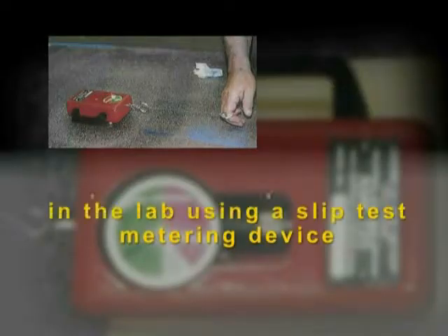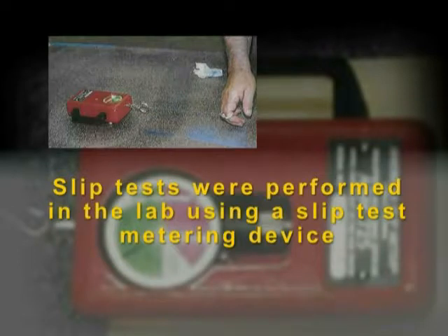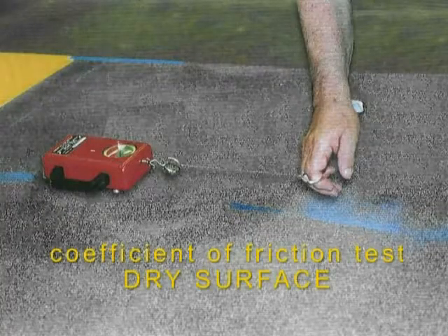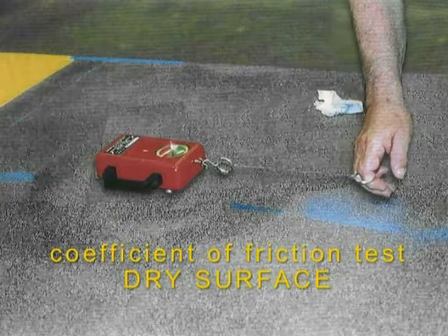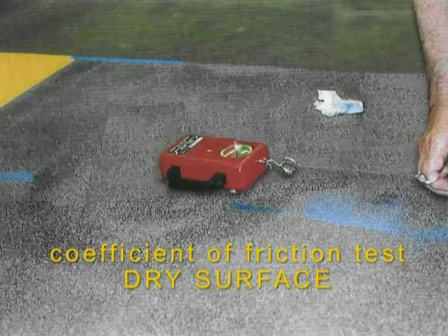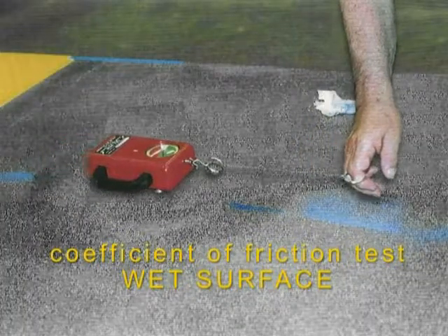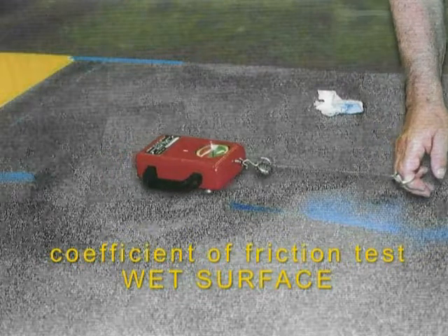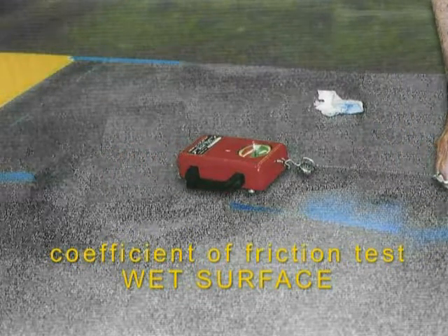We performed in the lab slip tests based on an ASTM standard test method with a standard slip device. It's a small weighted sled that has a texture on the bottom surface where it comes in contact with the product that's to be tested, and it's placed on the sample, and one measurement is taken on the force required to pull this test rig across the sample, and then the product surface is wetted with water and the test is performed again. And so there's a comparison of the dry and wet forces required to pull this weighted sled across the sample.